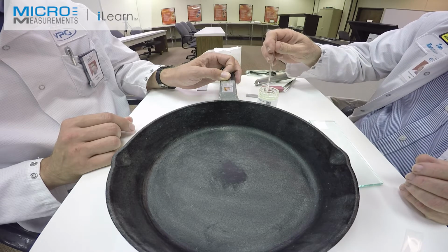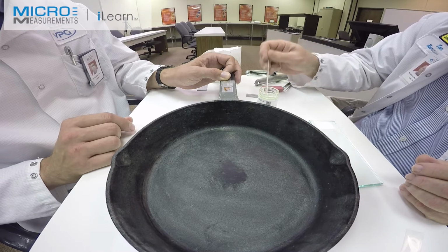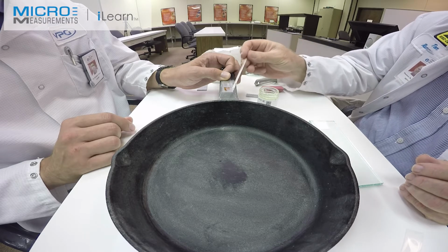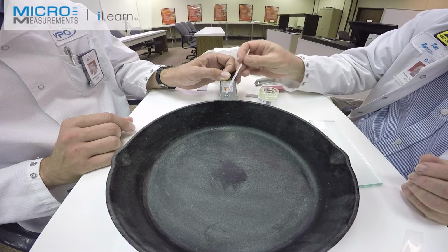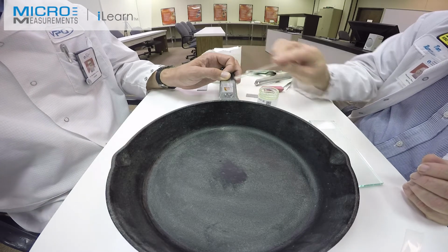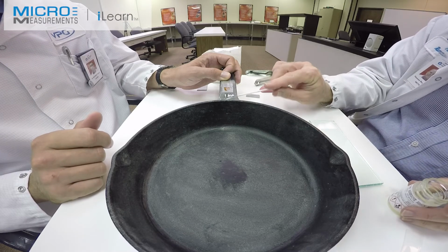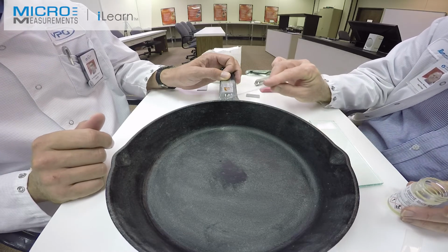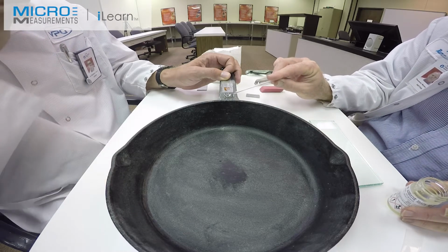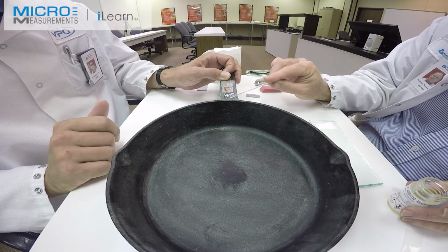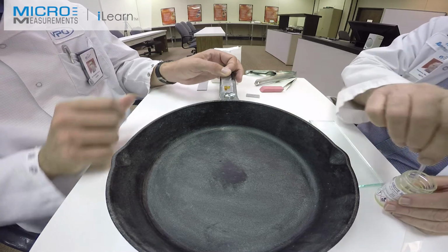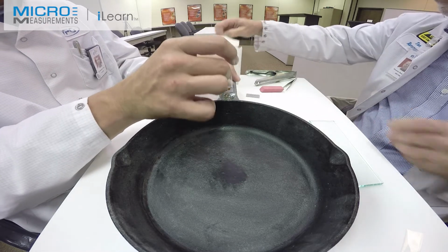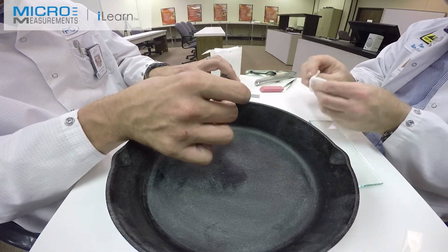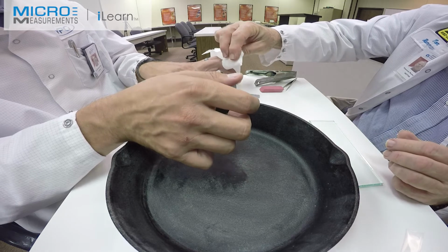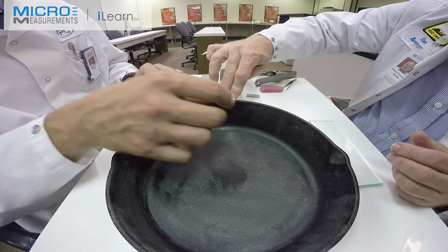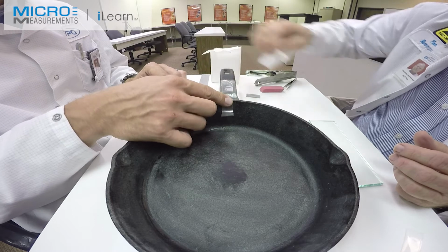Then I'm also going to take a drop of the adhesive, and I usually let 2 drops drop off of it before I start to minimize the adhesive. I'm also going to put that in the target area where the gauge is going to land. This thoroughly wets the surface so we don't have a starved bond line. Notice I'm using the side of the stirring rod as a squeegee. And now we'll return that back into position. I'm not bearing down as I'm pushing this in place. Just kind of push it out, and then you kind of wipe away the excess.